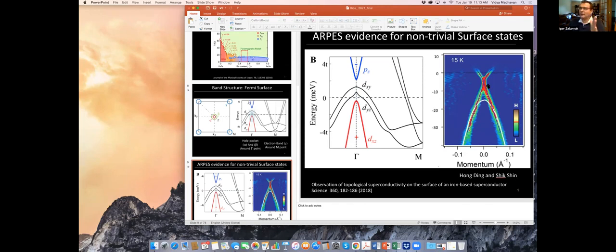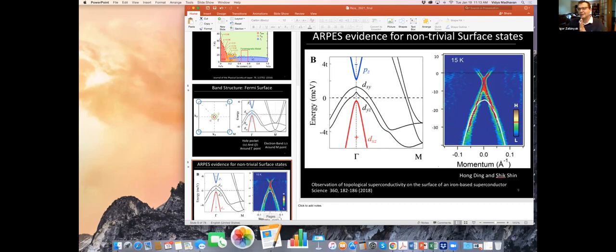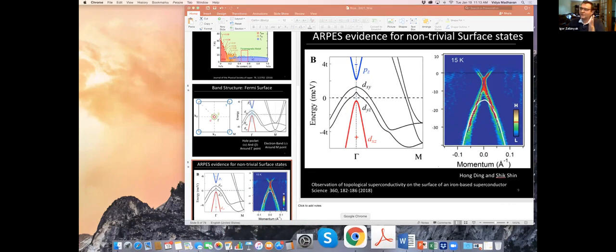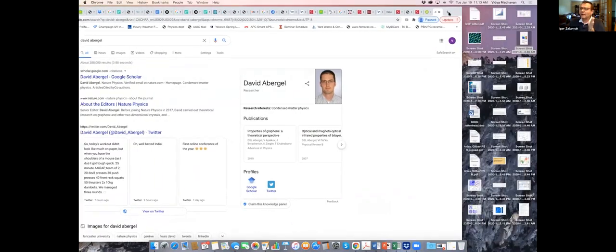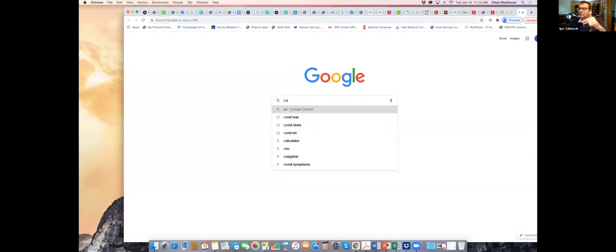So there is a phase diagram that has been recently established of topological superconductivity, non-topological superconductivity, and in fact, the non-superconducting state at the excess of iron, which begins roughly at a stoichiometric composition of iron 1. So this phase diagram is basically similar to the famous phase diagram of correlated materials in the strong spin-orbit regime. So x, the iron composition, quantifies the correlation effect, and y, the tellurium composition, quantifies the strong spin-orbit coupling effect.